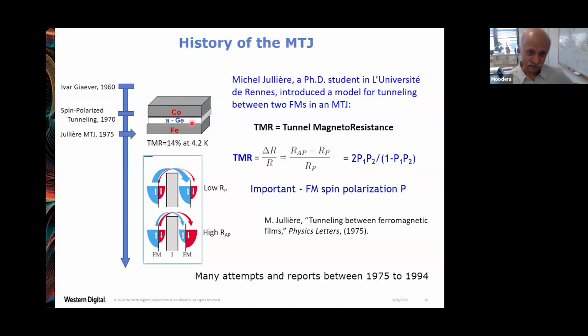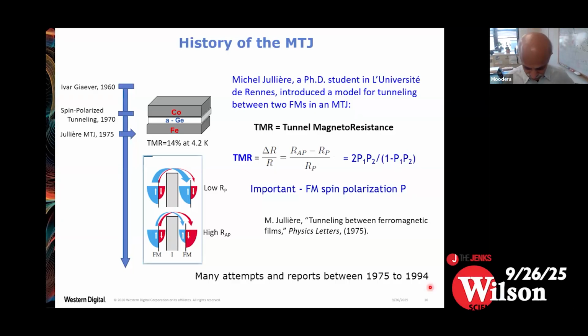Now, if you reverse the magnetization of one of the electrodes, that means you make them anti-parallel to each other. Then this large number of carriers here don't find enough places to go, and the current drops. Same thing with the other one too. You have a smaller number of minority spins, but they have lots of states here. Once again, the current flow is not enough. So between these two states, by just changing the magnetization from parallel to anti-parallel, you can have a very large tunnel magnetoresistance. This was 1975, as you can see here. That's when Julliere came up with this model. And there were a lot of attempts between 1975 and 1994. Everybody wanted to realize this simple model and this possibility of having a very large TMR, but that didn't happen.